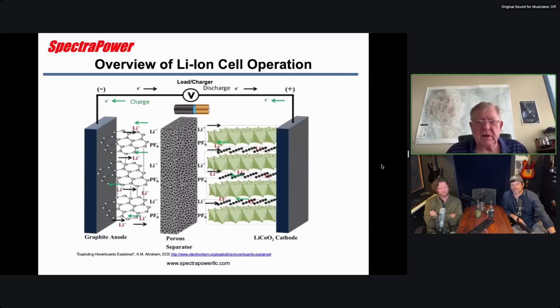And the other thing is, to justify the additional cost and difficulty, people typically want to use lithium metal because it gives you much higher energy density. So they replace this graphite, a carbon anode, with a solid sheet of lithium metal. And the idea is, well, the separator will make it safer, and it helps. But if you puncture that cell, you've got a problem. You've got exposure to lithium metal, and especially in an EV, in an accident, if you get water in there, then you've really got a serious problem.